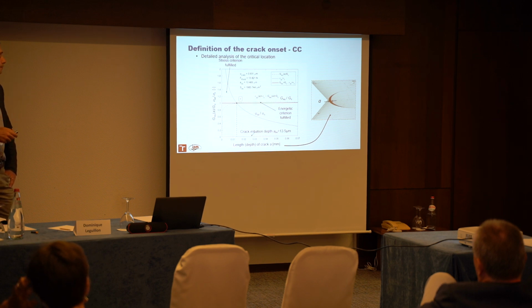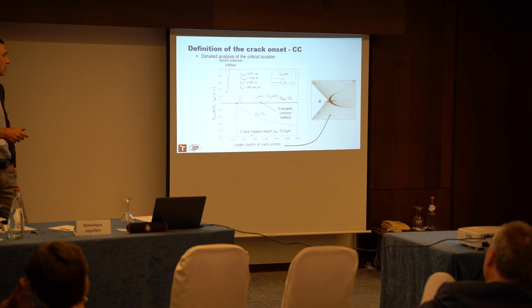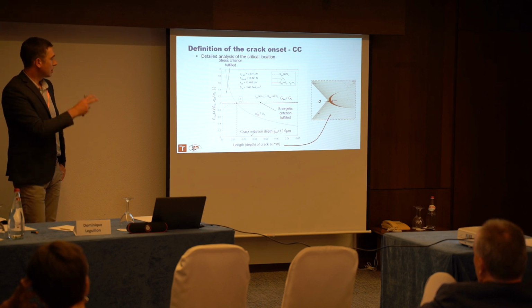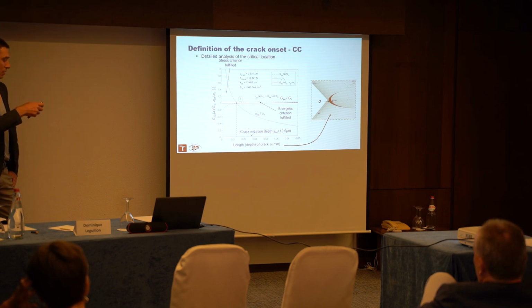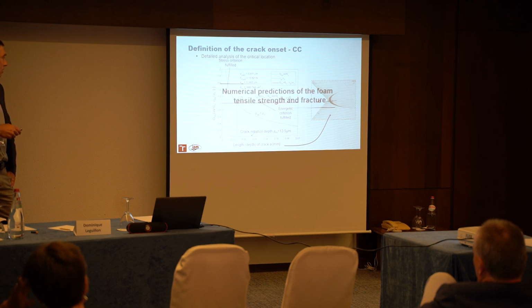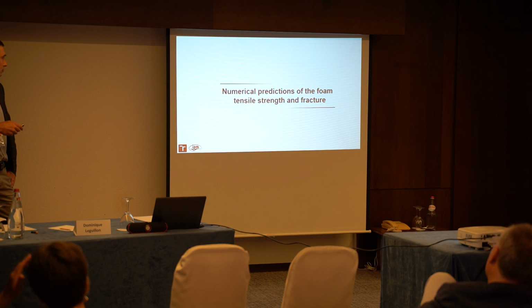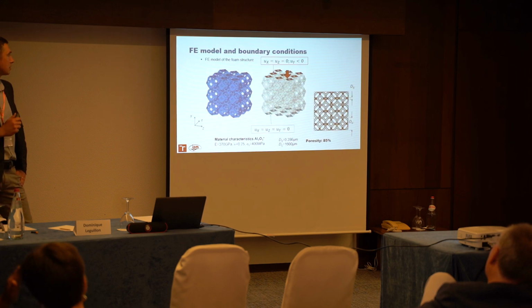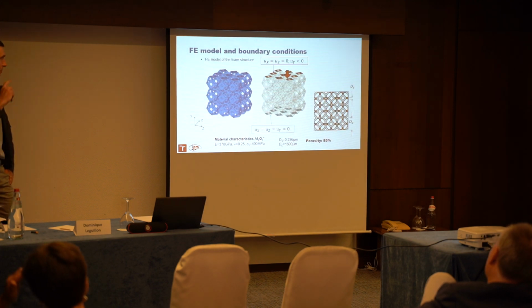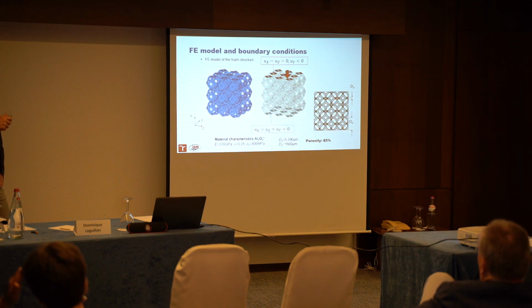So this is the important parameter. So this crack initiation depth is very important, since from this parameter we will then define fracture of the foam struts. So we can go further. Here are some numerical predictions of foam strength using this foam model.